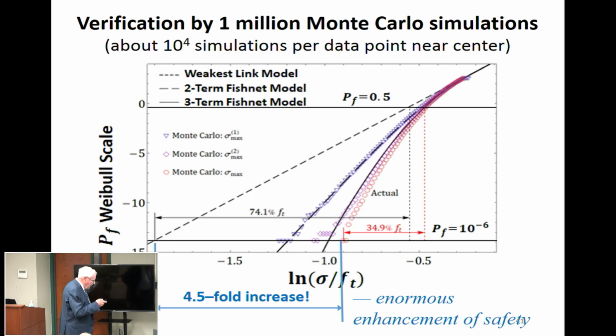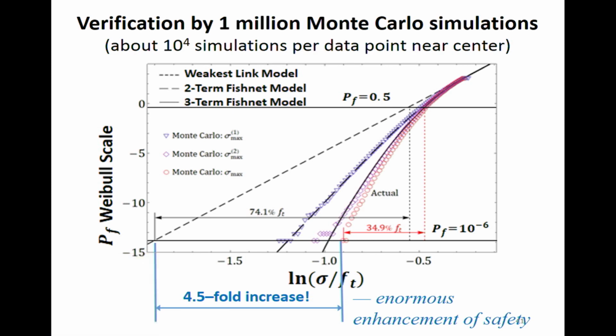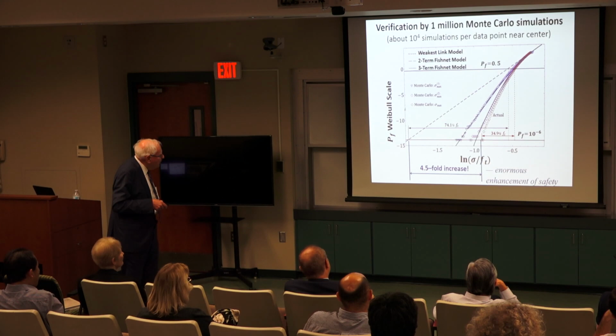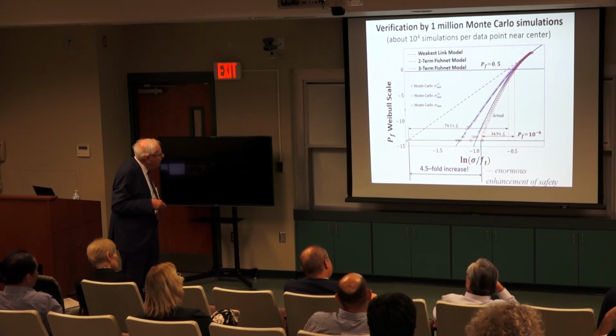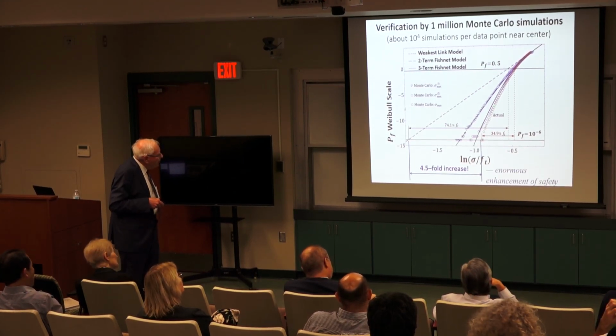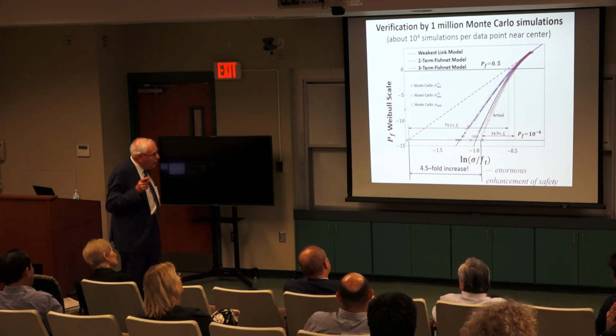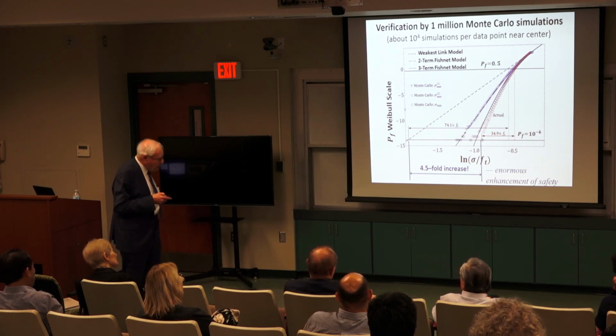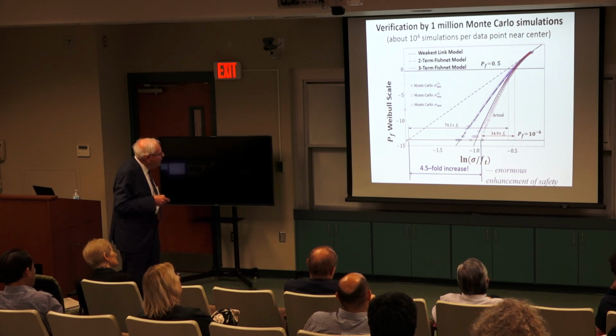Look at this result. So what Venlo did, he simulated these fishnets in MATLAB, such that for each case he ran 1 million simulations. I would have preferred 10 million at least, but it was good enough. This is the line of 10 power minus 6, and these diagrams are good up to about 10 power minus 5. This is becoming too scattered. Now each of these points is an aggregate of 10,000 simulations, okay?